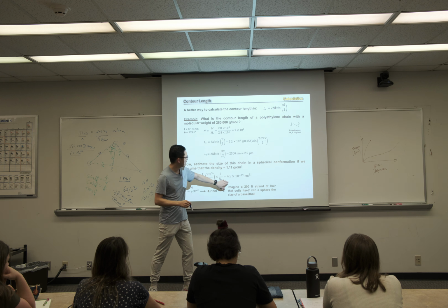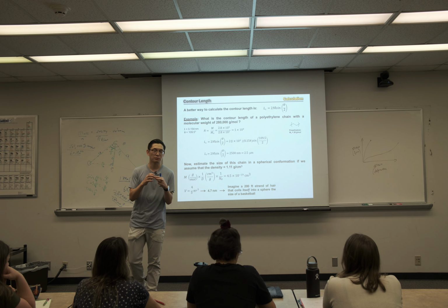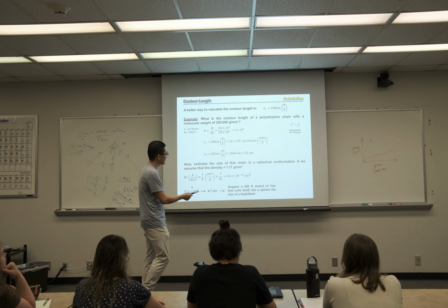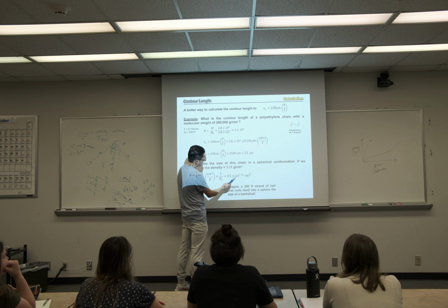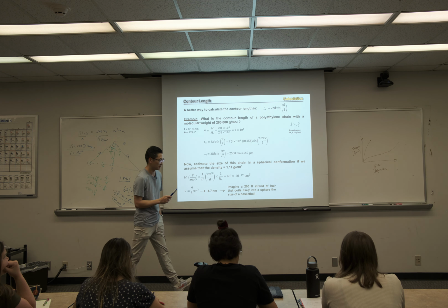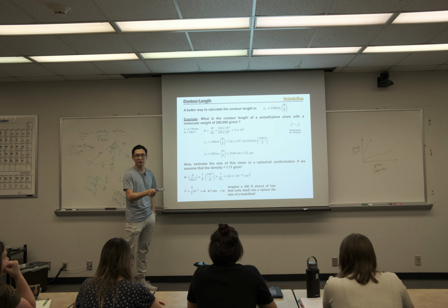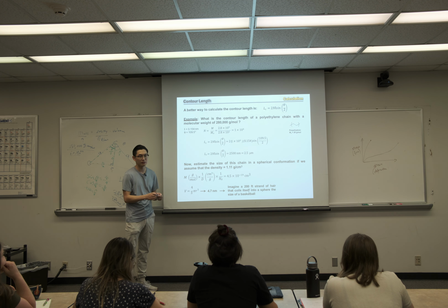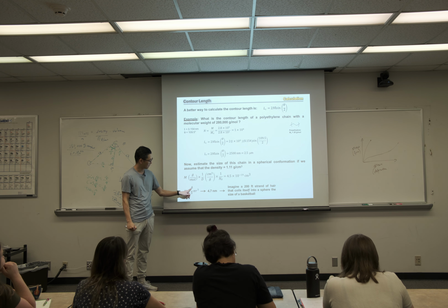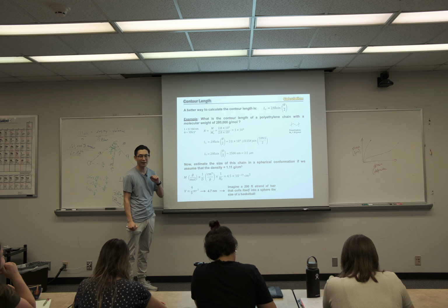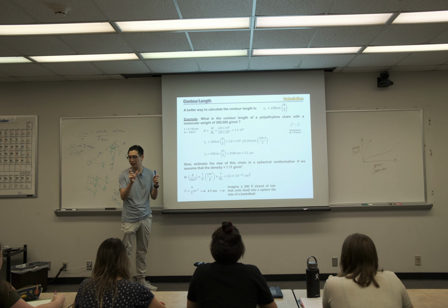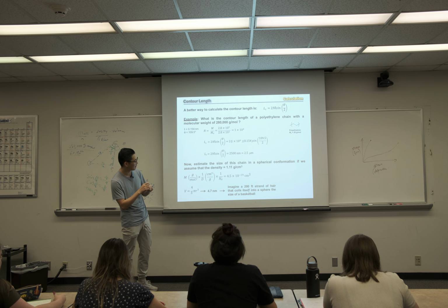This will give you the size for each individual molecule. So each individual molecule, if it's fully compact, is very tiny: 4.5 times 10 to the minus 19 cubic centimeters. If we assume it's a compact sphere, we get the volume from a sphere, because the volume of a sphere is calculated as 4/3 pi times r cubed. R is the radius of the ball. So if you know the volume, you can calculate how big your polymer is if it's really compact.